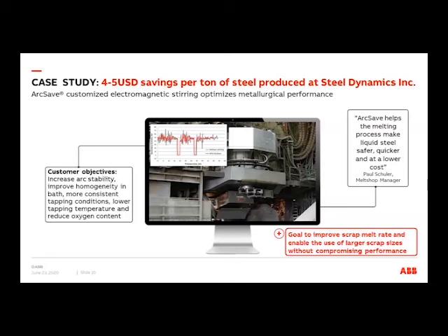As you can see regarding the arc stability, you see a diagram which shows the current fluctuations during melting and also flat bath operation. So you can see clearly that the current fluctuations are much less with the ArcSave. This is because we are creating liquid metal much faster. We have a much faster melting rate when we are melting the scrap, and therefore we are creating a more stabilized arc pattern. On the right, you see a quote from the former melt shop manager Paul Schuler.